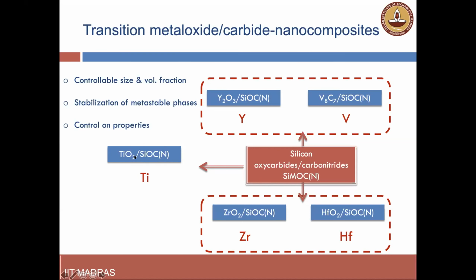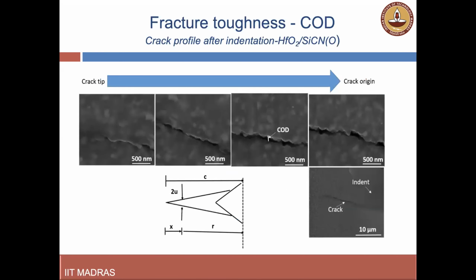In fact, we also showed that they are plasmonic in nature, and they can be considered as plasmonic, refractory kind of ceramic composites, which can be used again for some applications. We have published a paper in Materials & Design on photocatalytic properties of such plasmonic titania in silicon oxycarbide matrix. But anyway, the point is that we are now looking at making these materials much cheaper and relatively easy to handle, so that we can get more or less similar kind of properties.